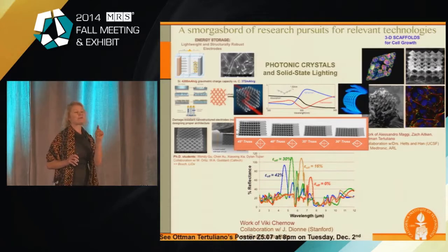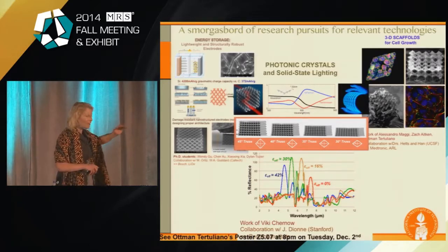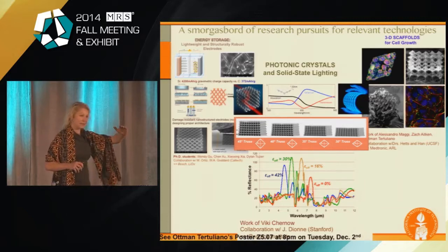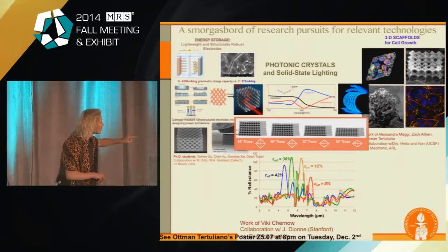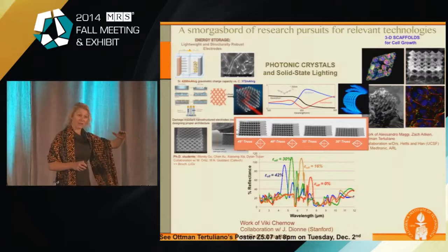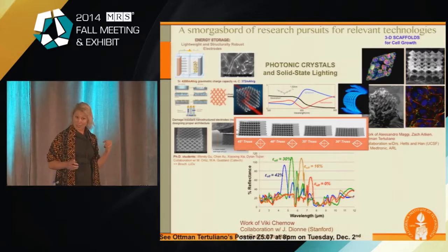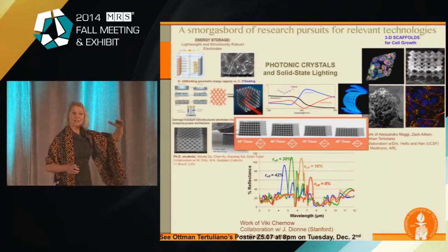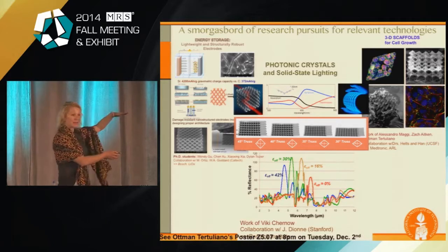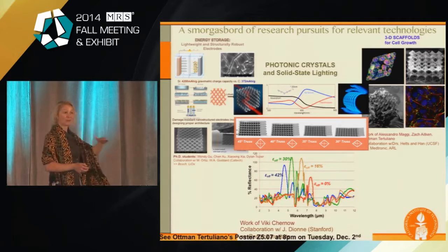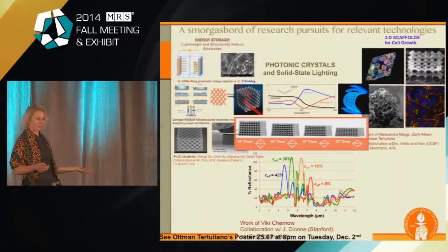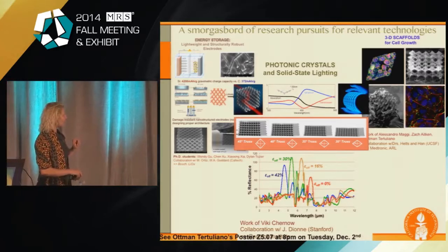But the reason why it's important that they're made out of polymer is that when you compress them, as I show here, they compress homogeneously, and that is uniformly, right? So the overall Bragg spacing here gets reduced all at the same time, not like the layer-by-layer collapse that I showed you earlier, where part of the structure stayed completely intact and all the other layers were doing the layer-by-layer collapse. That wouldn't be a photonic crystal. So Vicky figured out that you have to do this out of a polymer,